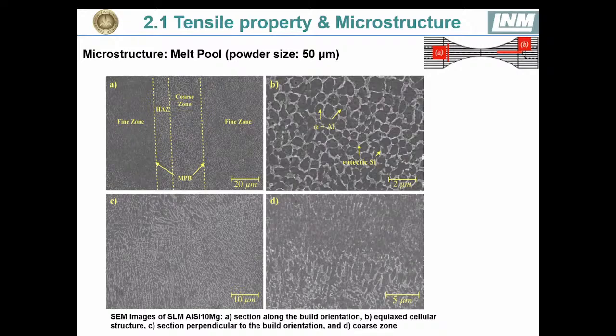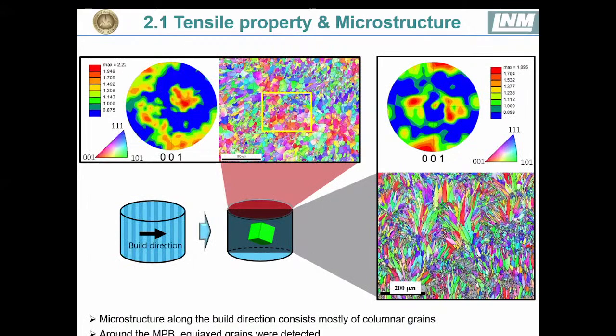Eutectic silicon is believed to improve the mechanical property of this material. And also in the fine zone and the coarse zone, we can see the anisotropic microstructure distribution of this material here. And the microstructure is further observed using EBSD here from different orientation, from different angle. We can see that in the direction of building direction, we can see some columnar grains, and this is formed due to the thermal gradient.